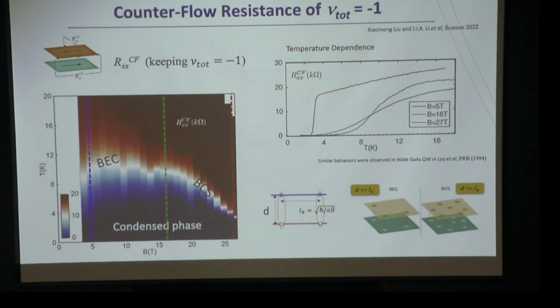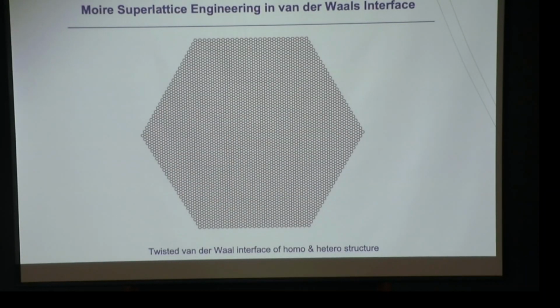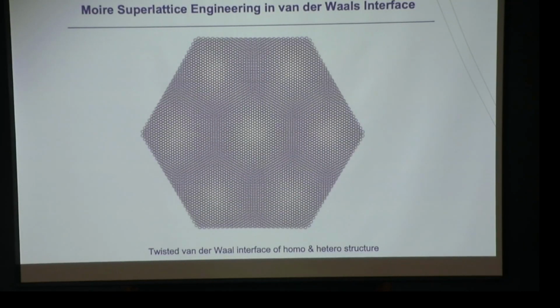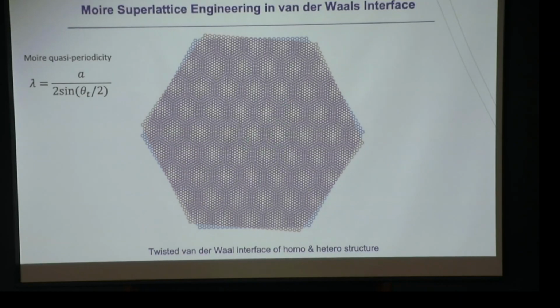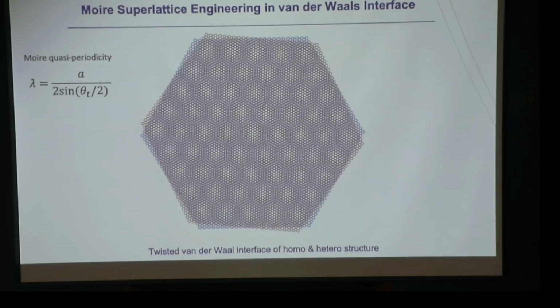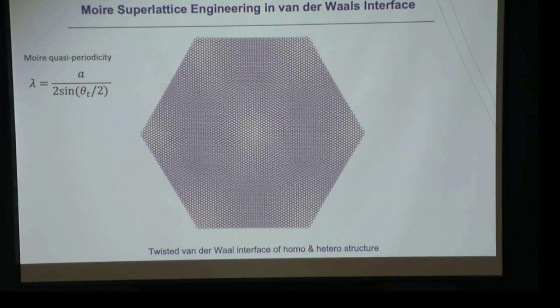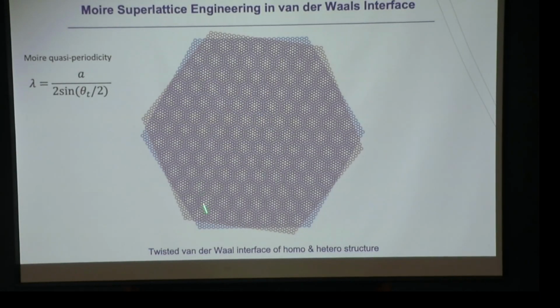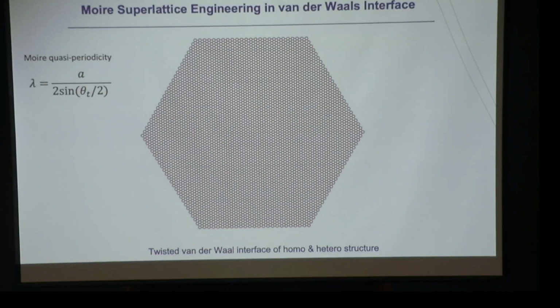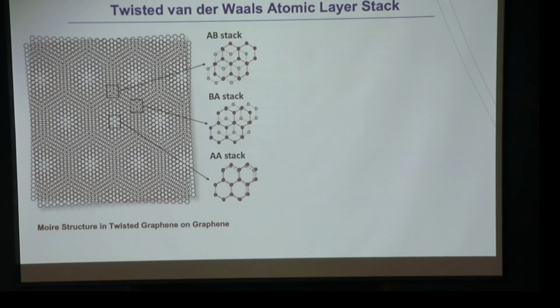Right. So I don't want to hold you too long, but of course, when it comes to two-dimensional systems, especially in the past few years, you cannot go around without talking about twisted layers, or twistronics. The idea of twistronics comes from this van der Waals layer system, because when you stack them together, they can be stacked with any arbitrary or twisting angle. Quickly you can see that when you put these two layers together, because of the quasi-periodicity appearing from this twisting, there is a so-called moiré periodicity that appears, which allows us to engineer the band structures of 2D systems. Not to mention graphene: when you put in some twist angle, those moiré patterns give you a somewhat different type of quasi-periodicity.